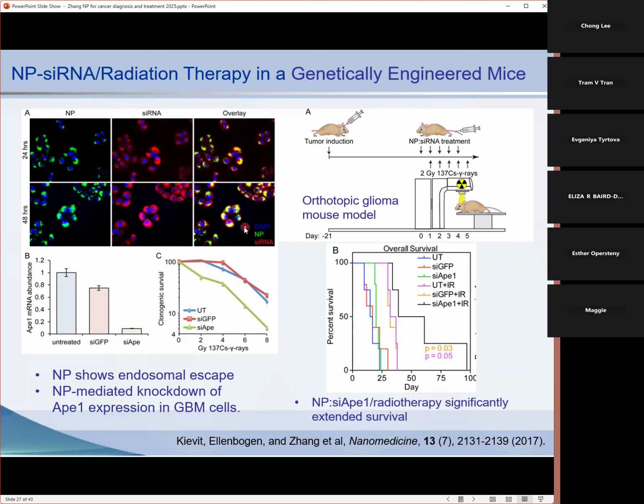So once successful in vitro, then we apply them in vivo. So basically, the schedule is usually tumor inoculation, then injecting nanoparticle siRNA 1 day before the treatment, then collecting 1 day after treatment, so we give them enough time. So we also show that our nanoparticle design really shows extended survival compared to the other control nanoparticle, untreated mice, or mice treated with radiation only.